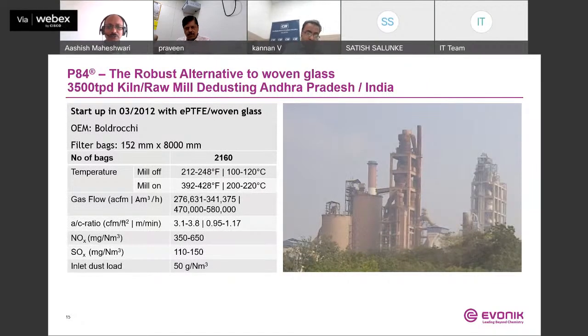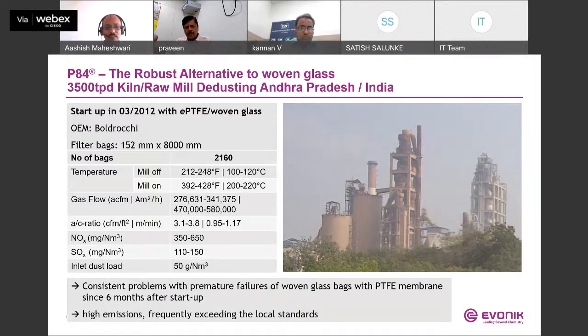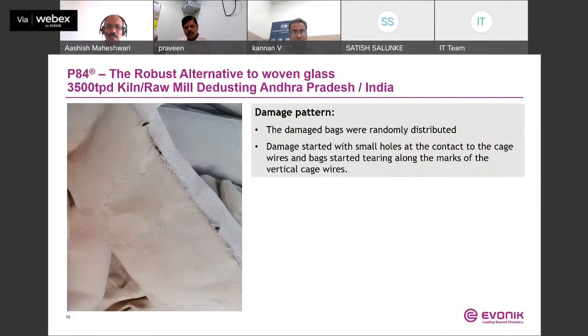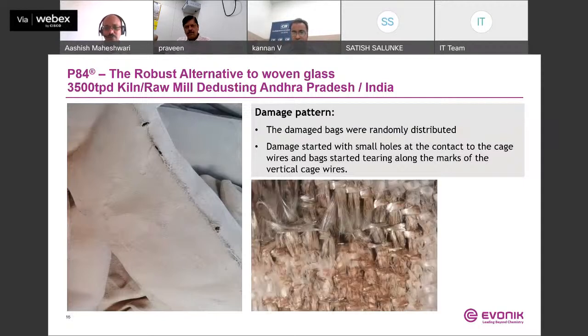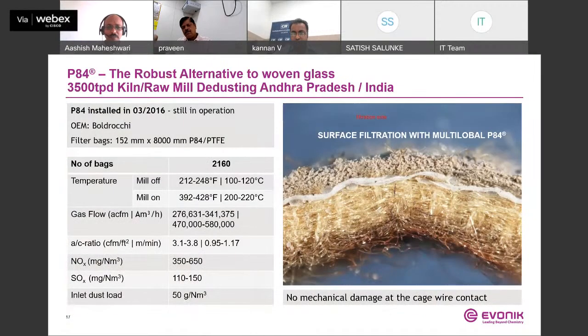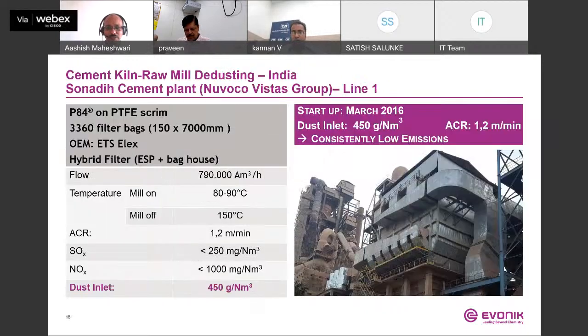This is a plant in Andhra Pradesh. Earlier it was with glass membrane, PTFE membrane, designed by Boldrocchi for 150 diameter, 8 meter long bags. The major failures were premature failure of the woven glass fiber and high emissions. So we analyzed the filter bags in our lab in Austria. We found that the damage was at random places, and there were punctures and holes because of the vertical cage wire. So the dust was penetrating and mechanical damage was taking place. We recommended P84 on PTFE scrim, and the plant is running fantastic without any challenges.